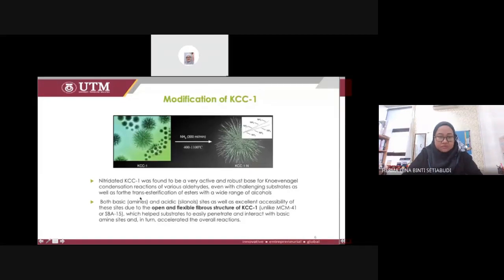Okay, this amine acts as a basic site, and then the silanol, actually in the fibrous there are many silanol groups, and these silanols contribute the acidic site. So both of these properties, as well as excellent accessibility of their sites due to the open and flexible fibrous silica KCC1, because of the many fibers here. So because of the good accessibility,